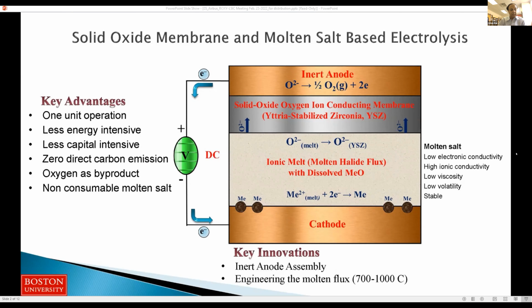The property requirements for the molten halide salt electrolyte are listed. It needs to have low electronic conductivity, so larger potentials can be applied without destabilizing the membrane. High ionic conductivity to reduce cell resistance, low viscosity for faster transport, low volatility for compositional stability, and chemical stability in contact with the membrane for long-term operations. Key innovations include anode design and assembly, and engineering the molten salt electrolyte to have all the required properties. Next slide, please.